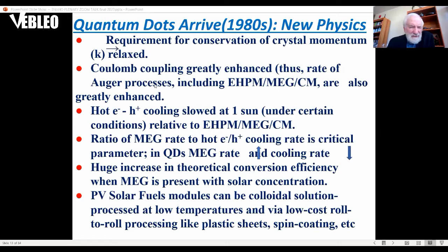And that's very important because it allows the process of multiplication of the electron-hole pairs, which are called excitons in the nanoparticle, because they're confined and the electrons and holes interact and associate with each other into an exciton. You enhance the Auger process. You slow down the cooling. You have a big increase in the theoretical efficiency because you can use the hot electrons either to produce multiple electron-hole pairs, or you can extract them before they cool to produce a higher voltage. The multiplication produces a higher photocurrent.